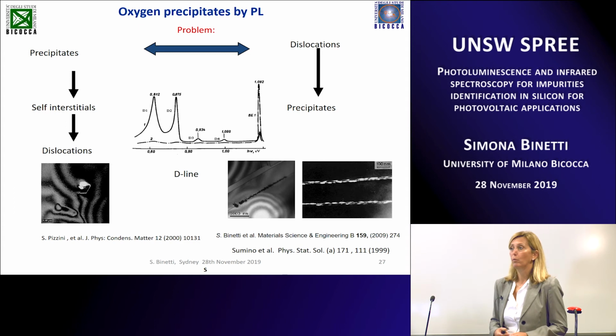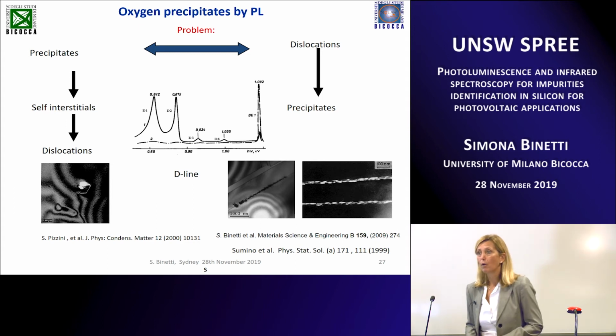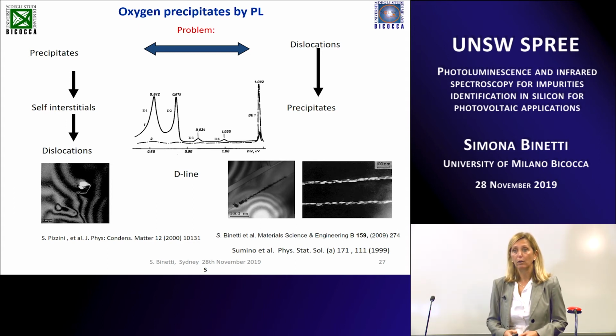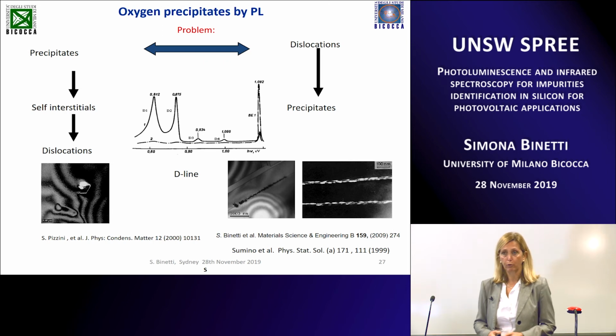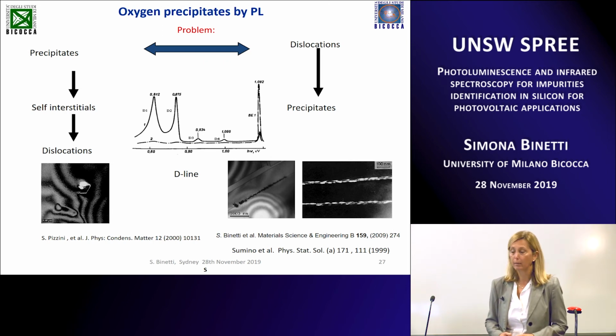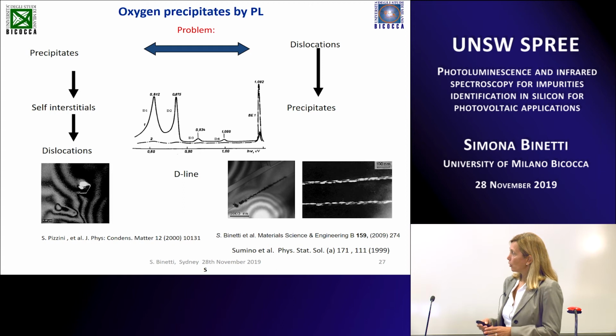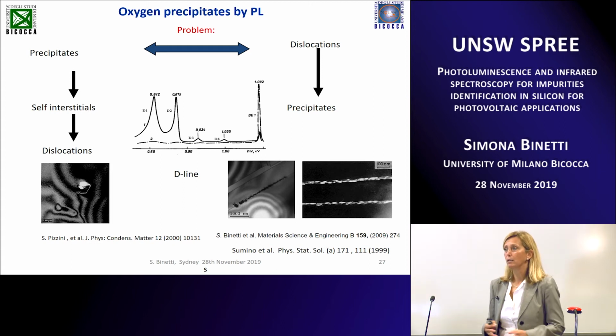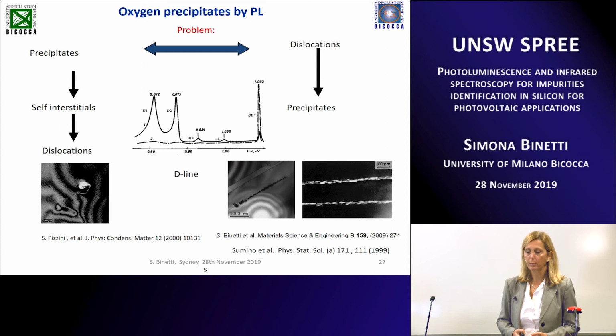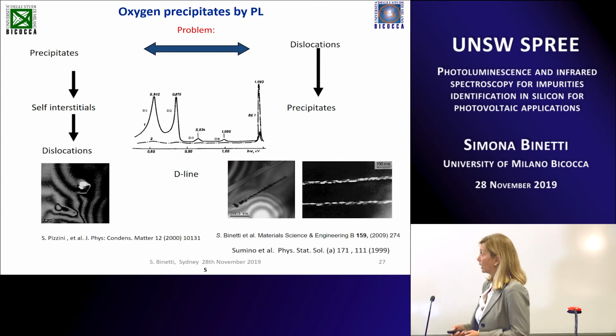But we know that when we have a dislocation in our sample, we have the very well-known D1, D2, D3, and D4 bands that can be identified by photoluminescence. So if you have both oxygen precipitates and dislocation, it's not so trivial to understand which band is related to oxygen precipitates or is related to dislocation.